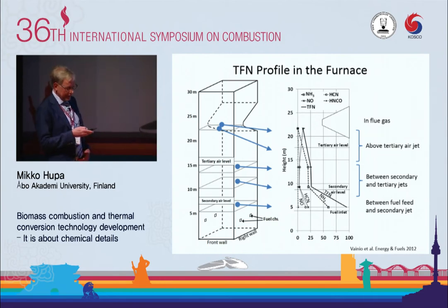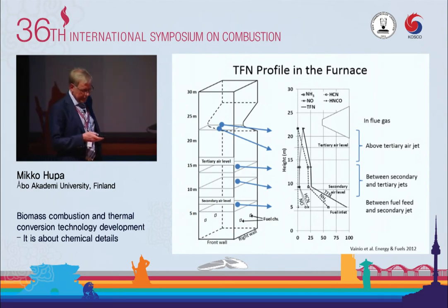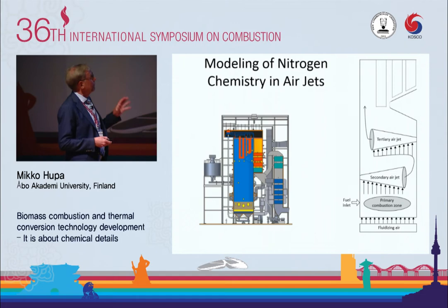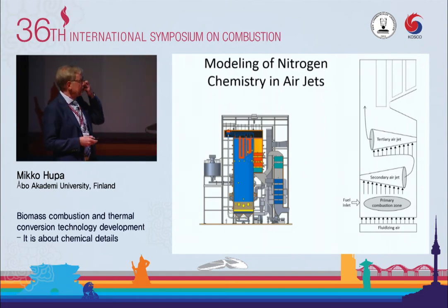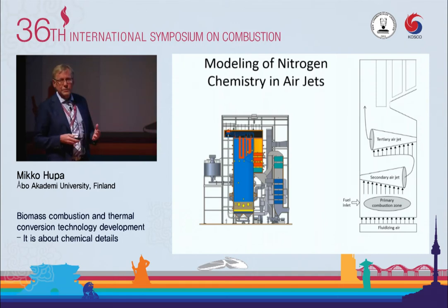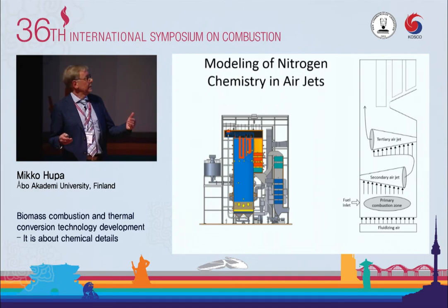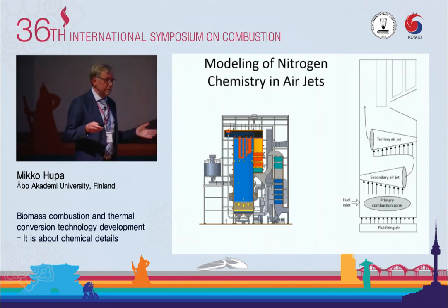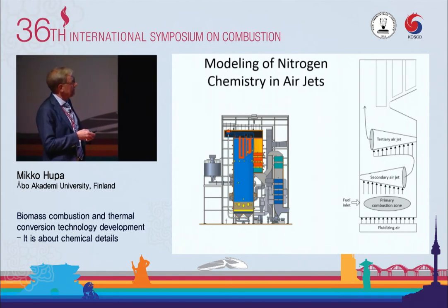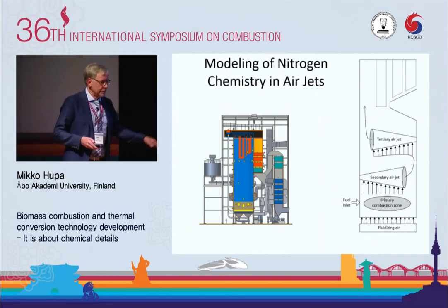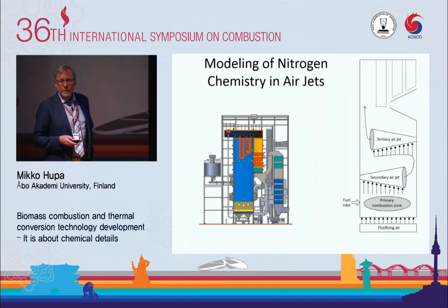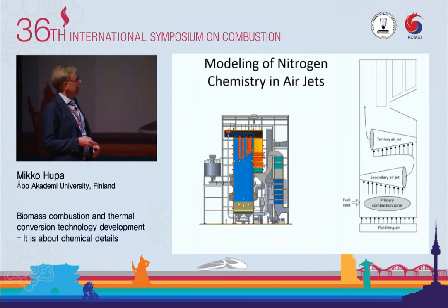So this was something that came by itself, and we were quite curious how to explain this. Here we thought that we may try to use some modeling, because the special feature with these units is that their air distribution is quite a new type. It's very heavy jets. These air jets are about 7-8 meters long with a velocity of 60-70 meters per second when they come in. So they form a very, very heavy horizontal jet. And we thought that maybe these heavy jets have something to do with this effect.